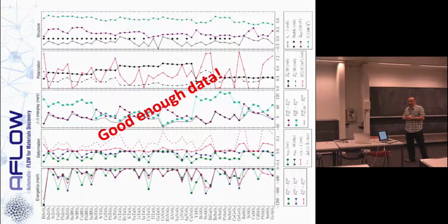They were only interested in structural theme. And they didn't care if it's rhombohedral or tetragonal, right? It's a tiny distortion of the perovskite lattice. They care if it's a layered perovskite or bulk perovskite. So they care on a different scale, the energetic. So the data were completely useless for us. The energetics in barium titanate is of the order of the millirydberg, so we need to have better convergence.